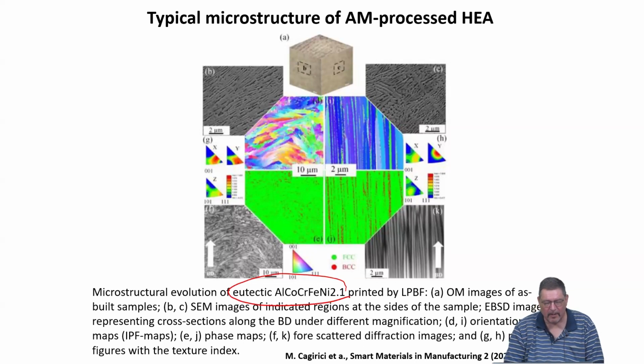And you can see that the microstructure variation is quite large, right? So the properties of this material would depend a lot on whether you look at the properties in transverse direction or building direction, because of these non-equiaxed structures that form. So you have elongated grains, you have dendrites which form. So it can be messy in terms of the microstructure you get from additive manufacturing. And one needs to really always analyze the microstructure in all three different directions in order to get a full picture of what really is the microstructure of the material. Just doing a planar cut through the microstructure like you normally do, polishing and looking at the cross-section, is not enough. You have to look at three cross-sections which are perpendicular.